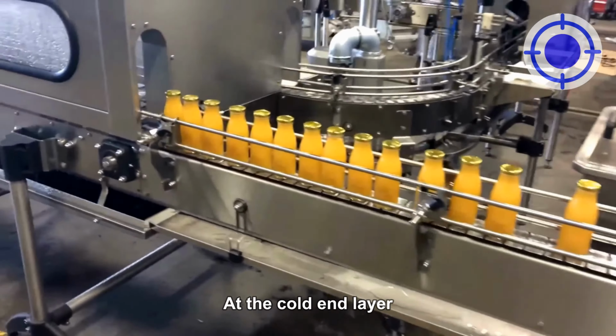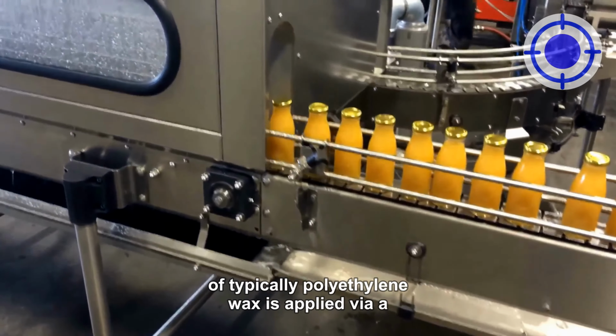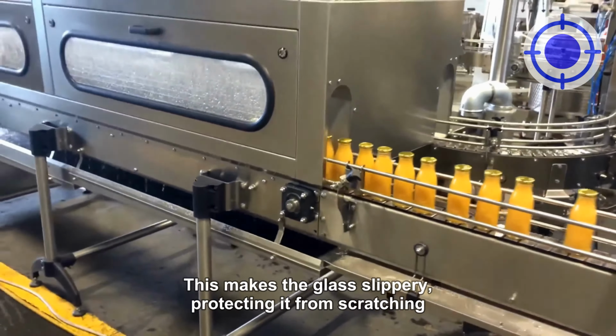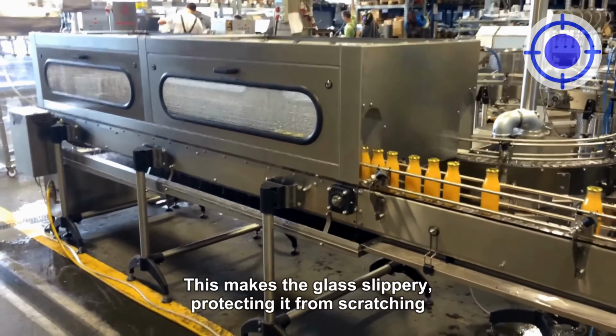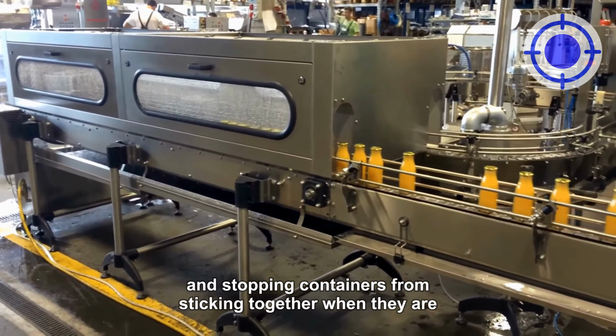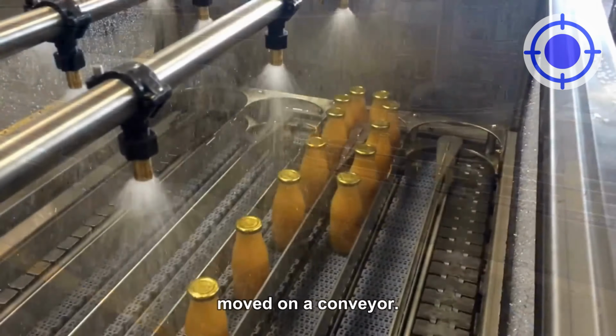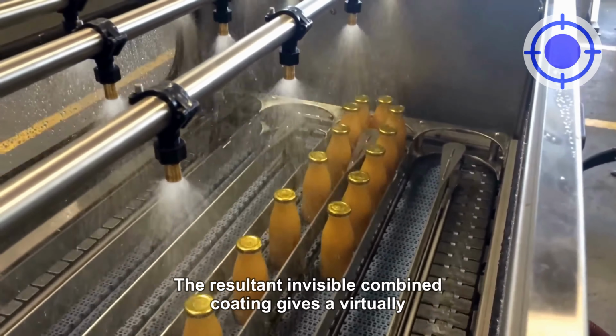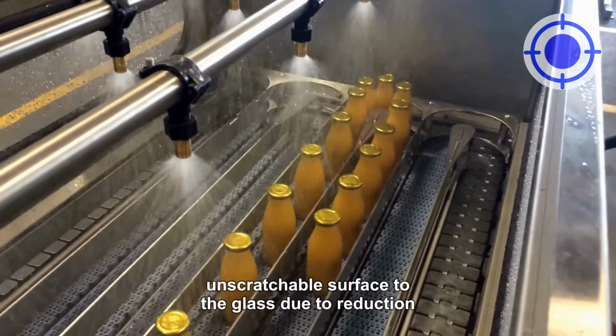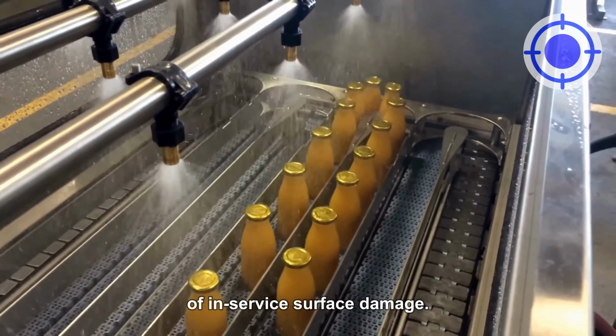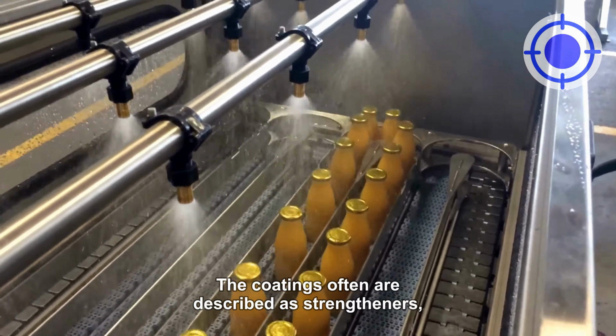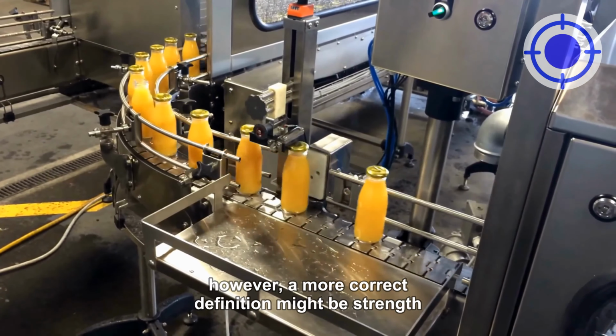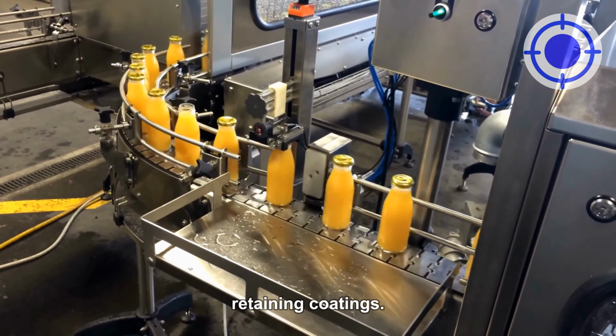At the cold end, a layer of typically polyethylene wax is applied via a water-based emulsion. This makes the glass slippery, protecting it from scratching and stopping containers from sticking together when they are moved on a conveyor. The resultant invisible combined coating gives a virtually unscratchable surface to the glass. Due to reduction of in-service surface damage, the coatings often are described as strengtheners. However, a more correct definition might be strength-retaining coatings.